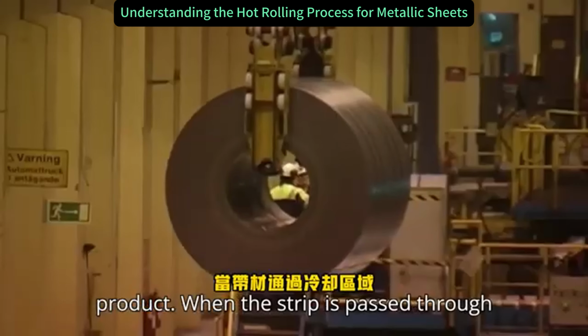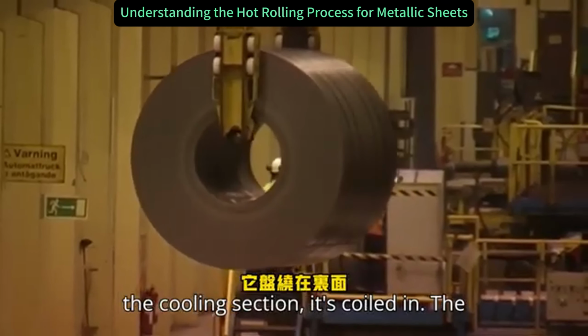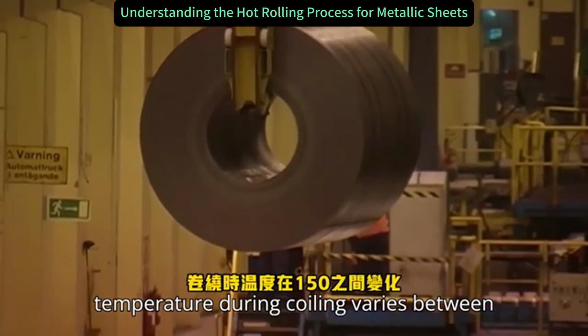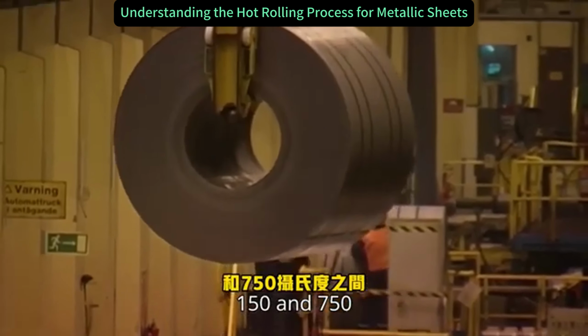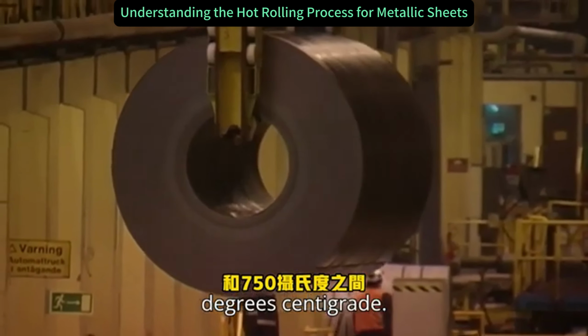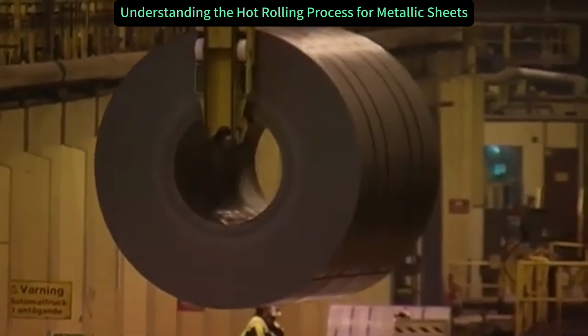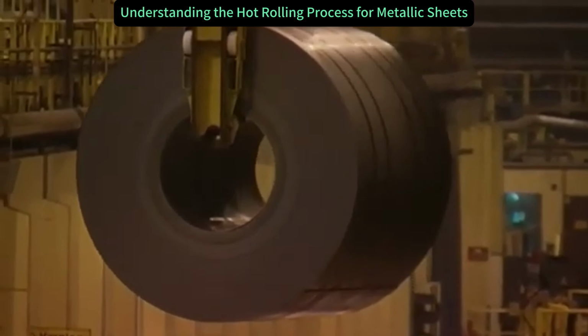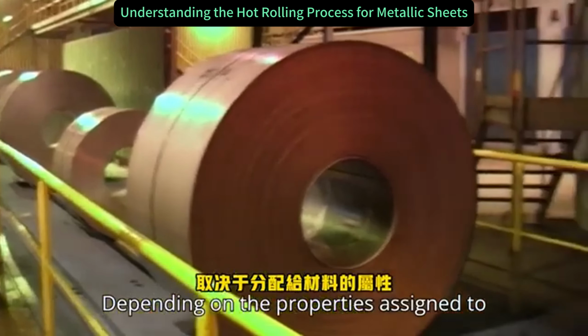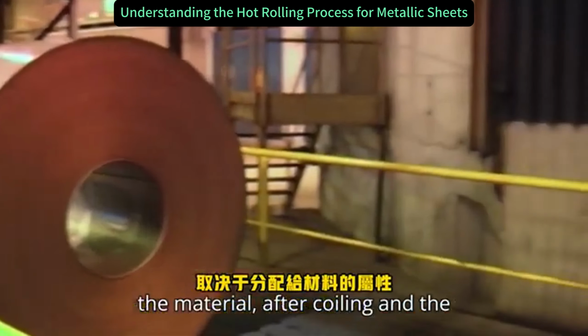When the strip is passed through the cooling section, it's coiled. The temperature during coiling varies between 150 and 750 degrees centigrade. Depending on the properties assigned to the material, after coiling and the subsequent cooling, the strip can be sold directly to the customer or undergo additional processing stages, for instance, cold rolling.